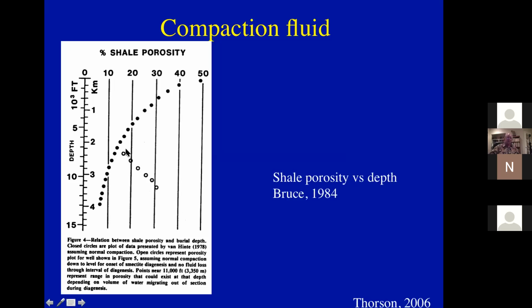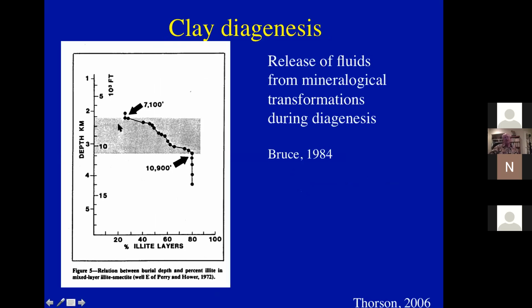And we'll take one short look at this little aberrant bunch of porosity data in the shales. What's happening is that at a certain depth, between 2 and 3, around 3 kilometers, smectite or montmorillonite is recrystallizing to illite. In this one well example, it started at about 7,100 feet, and the recrystallization finished at about 10,900. And so we're going from 25% illite layers in the clay to nearly 80% illite layers in the clay. That reaction releases water.